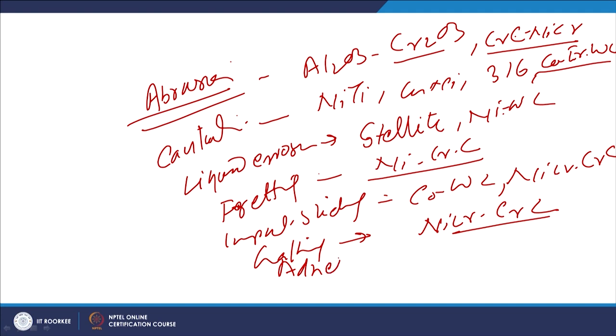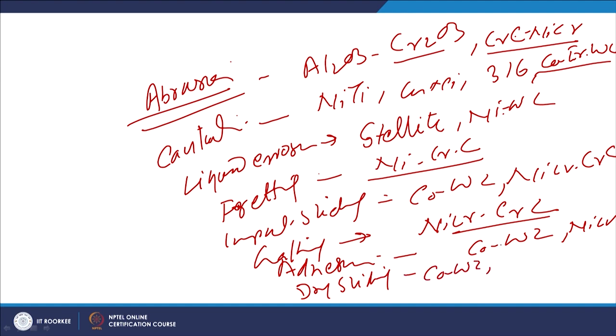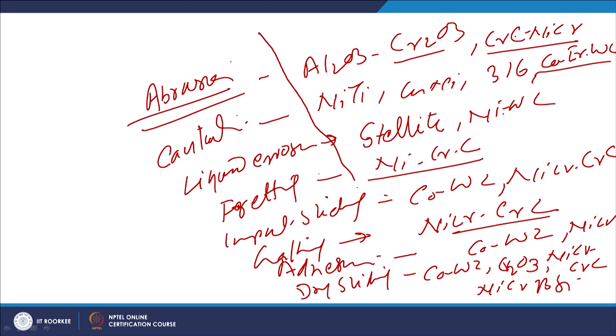For adhesive wear conditions, cobalt, tungsten carbide systems, nickel, chromium systems are used. And for the dry sliding conditions, cobalt, tungsten carbide, chromium oxide and nickel, chromium, chromium carbide systems, as well as nickel, chromium, boron, silicon systems are used. So, as per the kind of the wear conditions which are being experienced, the variety of the materials which are available can be used, so that suitable wear resistant functional surfaces can be developed in order to resist the wear.